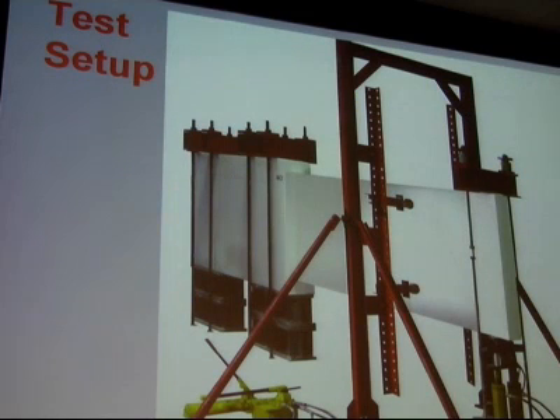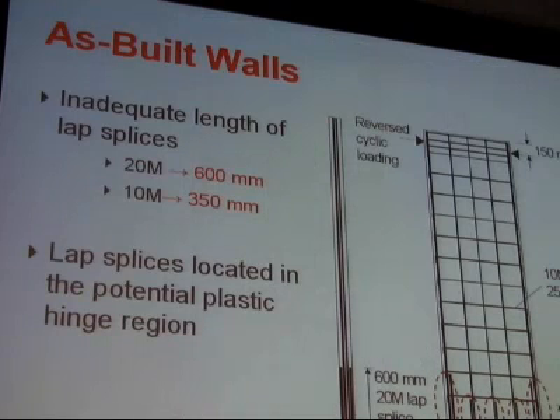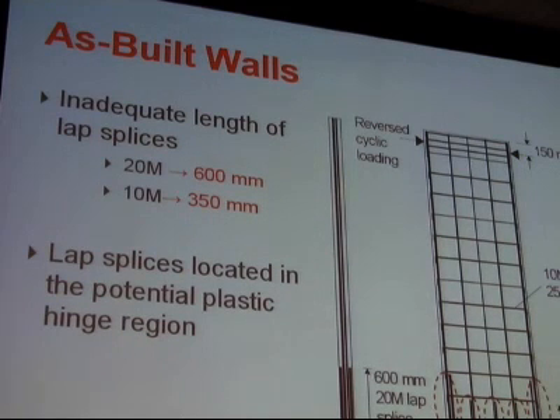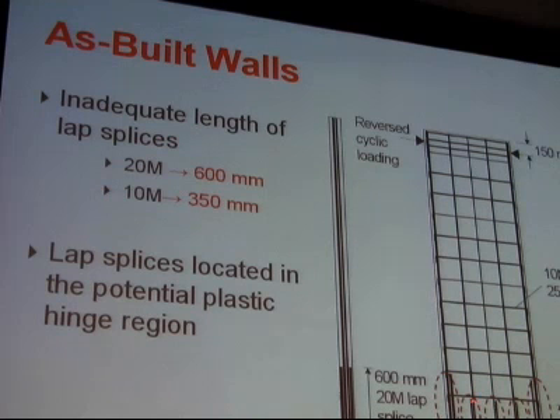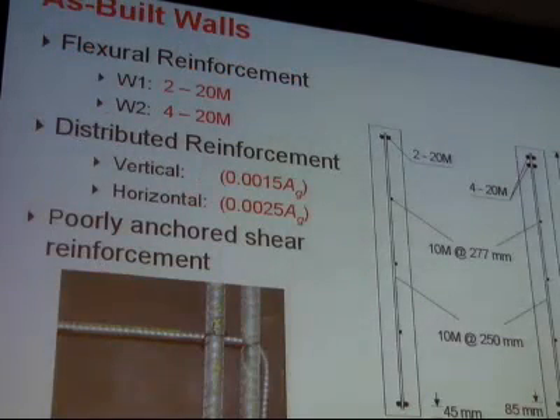So we've done a number of tests at McGill University. This shows the test setup that we've been using. We have typically a reverse cyclic loading at the tip of the wall, and the wall is fixed at the base. Notice that we're testing it in the horizontal position for the ease of testing. This is post-tensioned to the strong floor, and then we have guides here to prevent lateral movement. The series that we just finished some time ago involves lap splices at the bottom, the most critical section of the shear wall, of 30 bar diameters. We typically use 20M bars in these fairly thin walls. They're 150 millimeters thick. And this is very symbolic of the problems that exist in current construction.